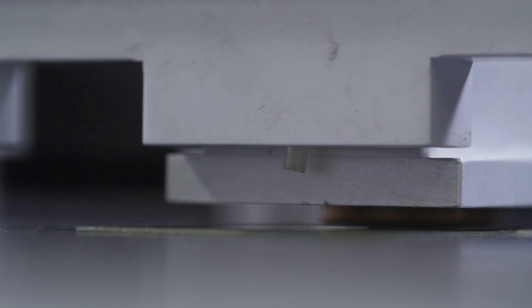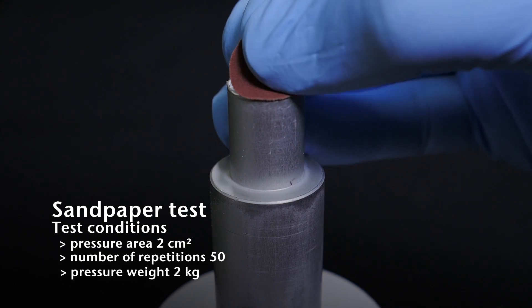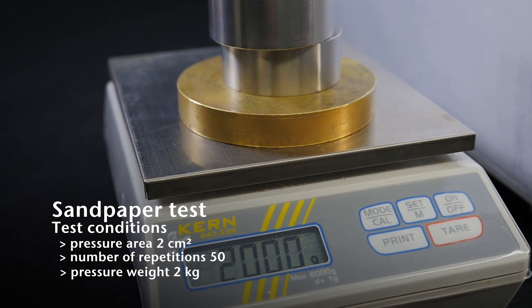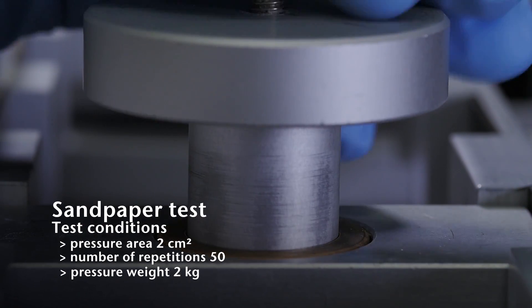But is this test sufficient to simulate real-life conditions of long and deep scratches? No, because it does not test sand, which is one of the big threats causing scratches. That is why Schott developed a new extreme abrasion test. It is based on Corundum sandpaper, which is harder than common sand grains and even four to five times as hard as a metal keyring. This test allows us to measure the scratch level accurately with a haze meter and to compare the results to other solutions.